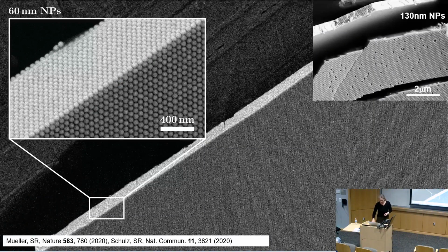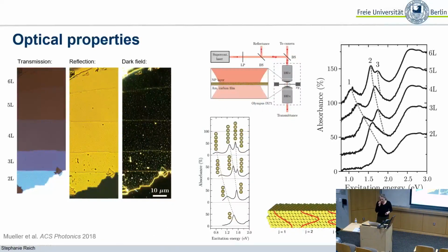So yeah, now let's see how we can measure these polaritons I spoke about and the optical response from this supercrystal. And the experiment is really easy and straightforward. We measure at the same time transmission and reflection from a gold nanoparticle film. So we take two microscope objectives. In between them, there is a gold nanoparticle film. Then we shine in light from a supercontinuum light source, and we measure the transmittance and the reflectance. To calculate the absorption, we calculate 100 minus reflection minus transmission, and that gives us the absorption strength.